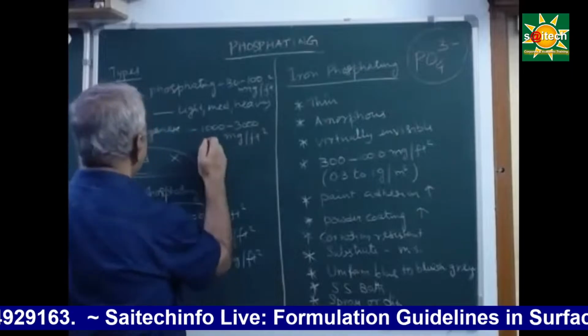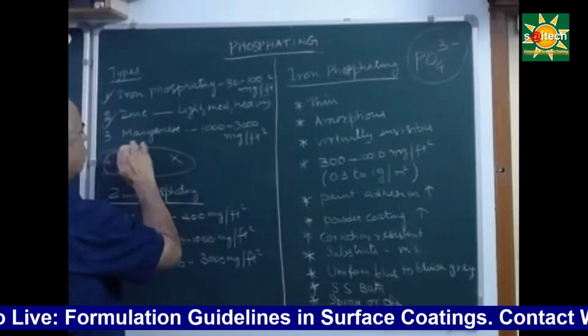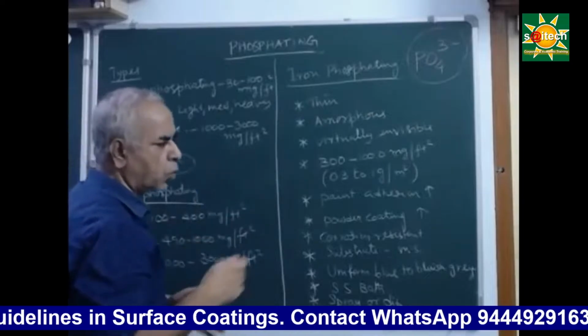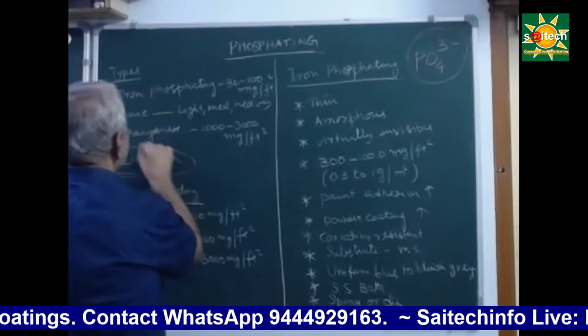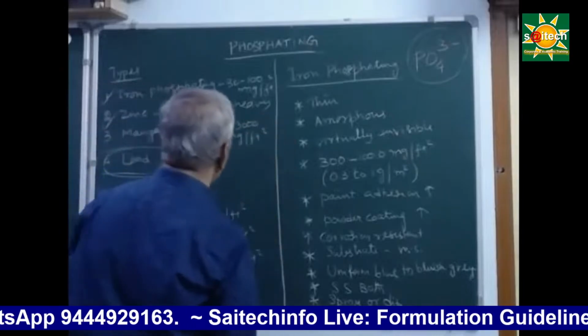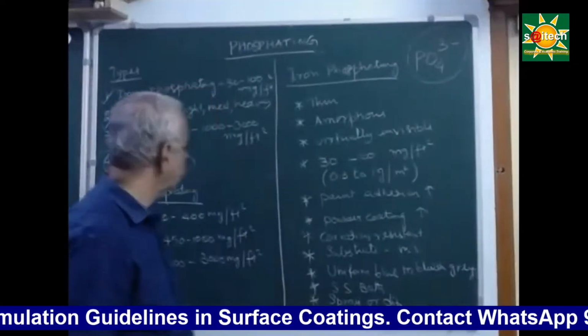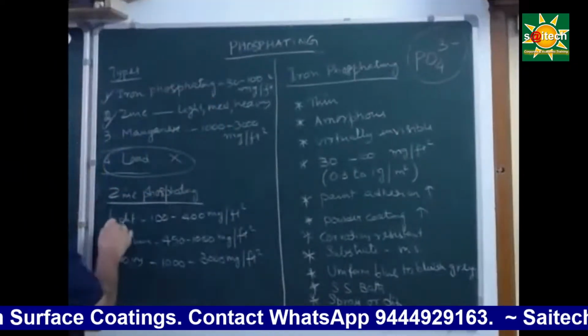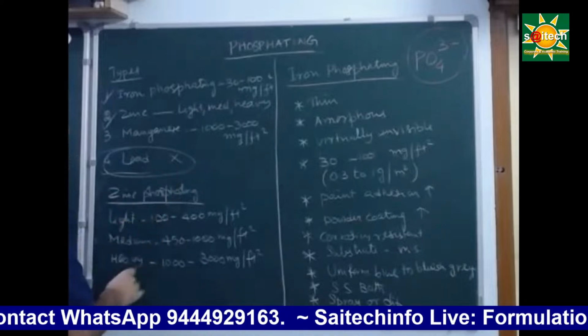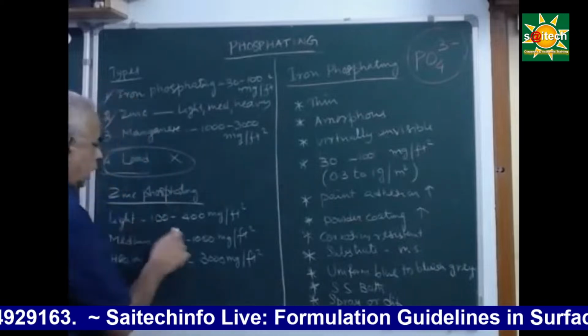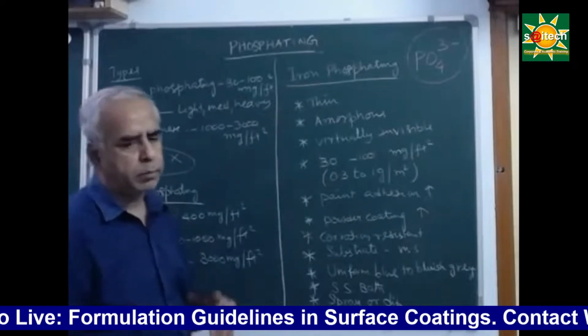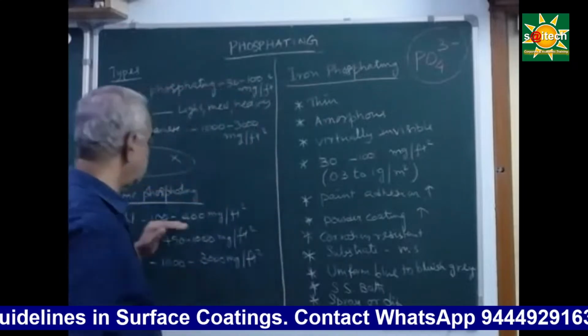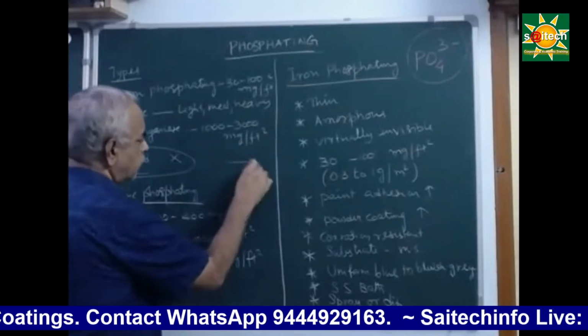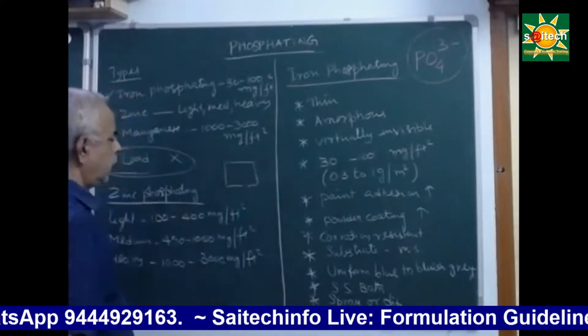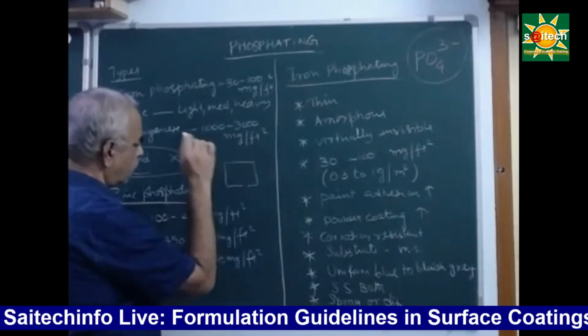It acts as a very good lubricant, and that is why it forms a very rough, porous surface of manganese phosphate. So for manganese, it is 1000 to 3000 milligram per square feet. Zinc phosphating has light, medium, and heavy types. Light has 100 to 400 milligram per square foot. That means for 1 square foot it can deposit 100 to 400 milligram.